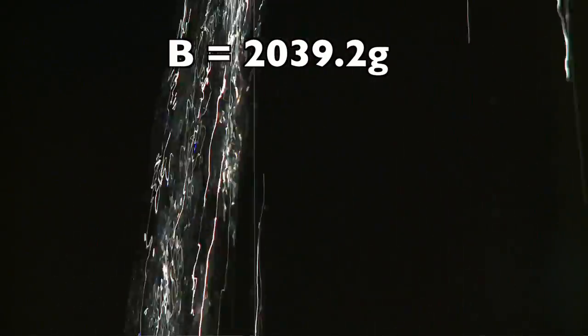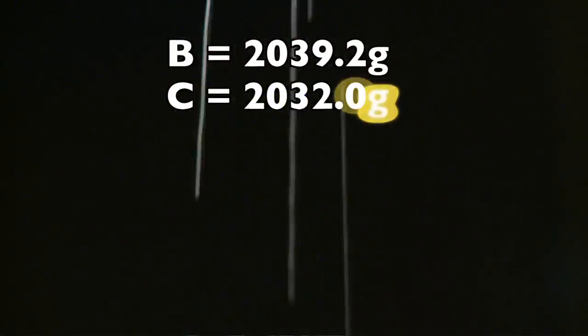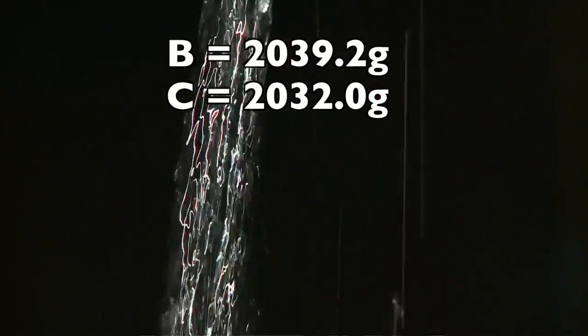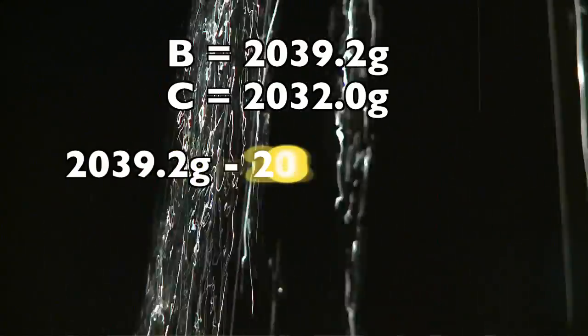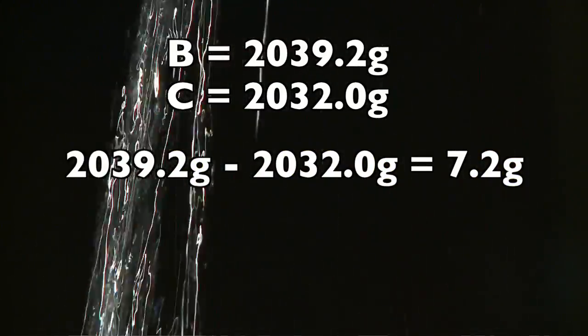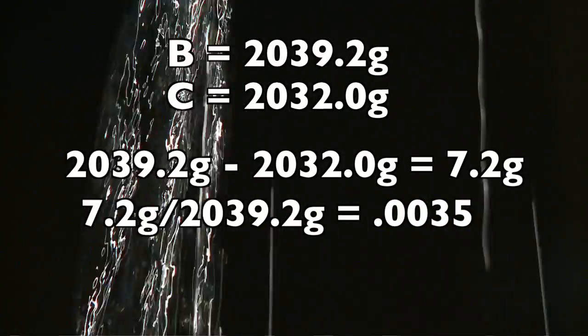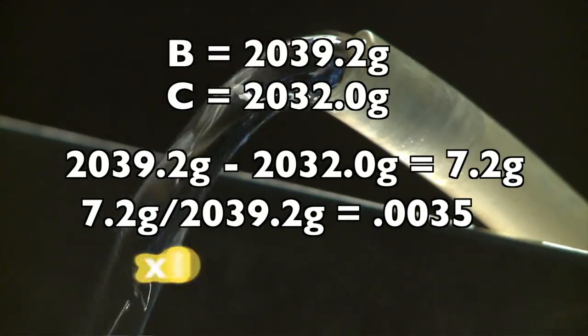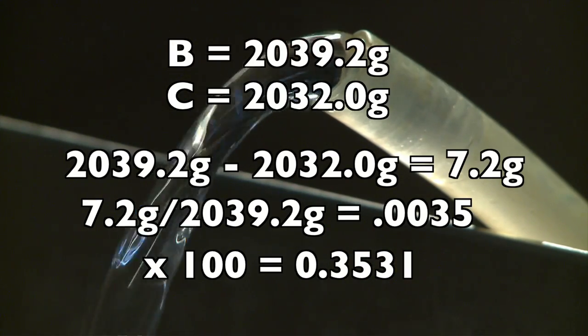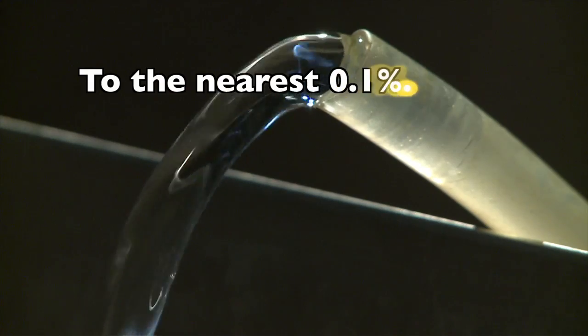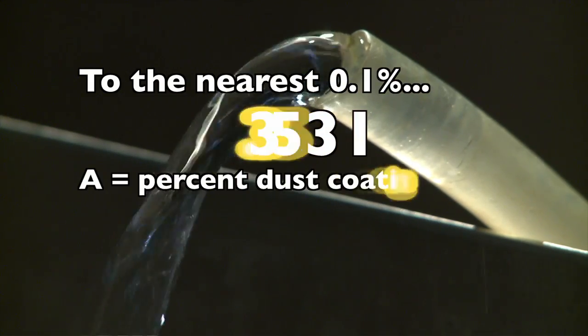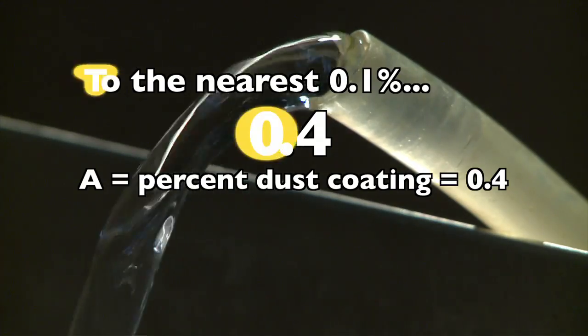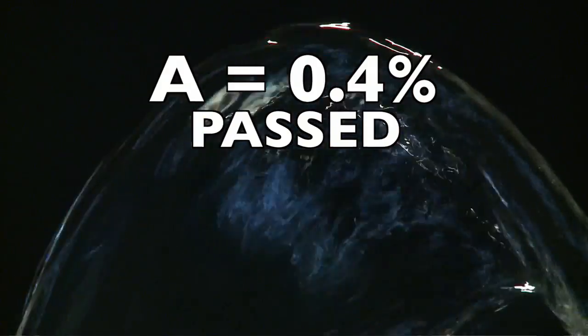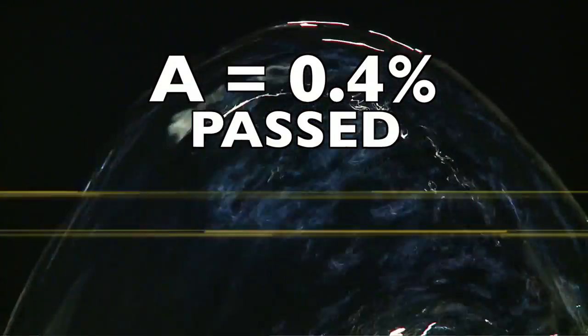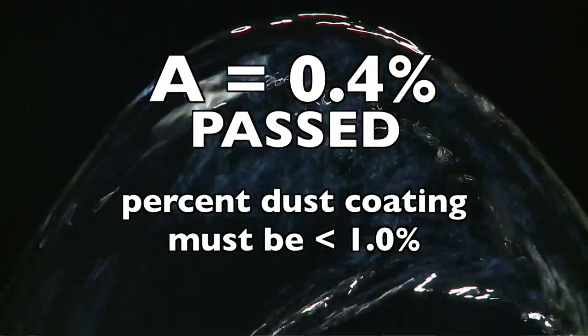In this example, the dry mass before washing is 2,039.2 grams. The dry mass after washing is 2,032.0 grams. B minus C equals 7.2 grams. Divided by B equals 0.0035. Times 100 equals 0.3531. To the nearest 0.1%, the result of this test should be reported as 0.4. In this example, the sample passed the ODOT requirement, which specifies a percent dust coating between 0 and 1.0%.